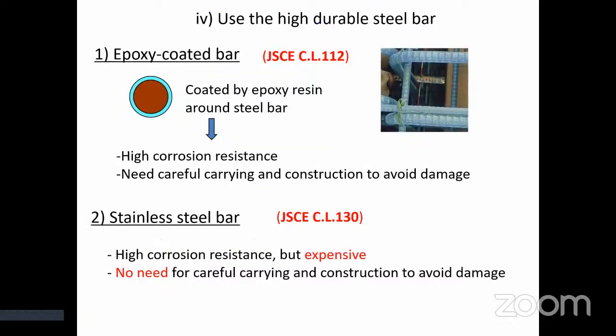Last one is using highly durable steel bars. One is epoxy coated bar. The steel surface is coated by epoxy resin. Therefore, it has high corrosion resistance. However, we need careful carrying and construction to avoid damage to the coating.